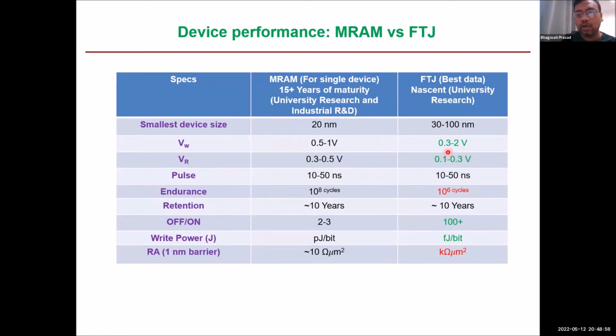If you see the write voltage, you need 0.3 to 2 volts. Read voltage is also in the same range or even smaller. Here the endurance is a problem, because you need a larger voltage to switch these devices, so you need to find systems where you can switch them at a smaller voltage. On the on to off ratio, this is where MRAM is not great, at only 2 to 3%, and that's why you cannot make a standalone memory with MRAM as of now. However, FTJ gives you an on to off ratio of more than 100. Write energy is also quite small, like 3 orders of magnitude smaller than MRAM.